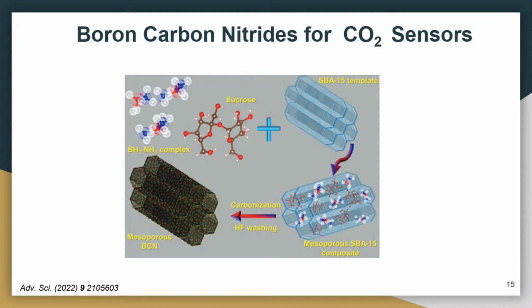So what we really did is we synthesized the mesoporous BCN structure, using the hard template method, right? We have taken the SBA-15 template. It's mesoporous, right? Then we used sucrose as a carbon source, and we have taken a boron-containing complex as the boron and carbon resource. And then we did the polymerization at 100 degrees Celsius overnight. Then we carbonized that at around 1000 degrees Celsius, at different temperatures we did, and we did the HF washing. Then we formed the mesoporous BCN, boron carbon nitride.